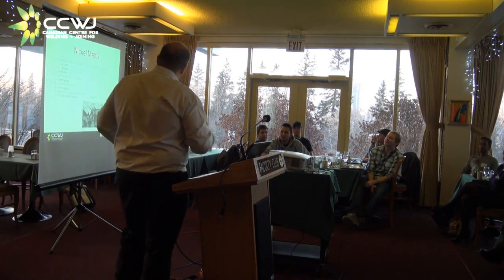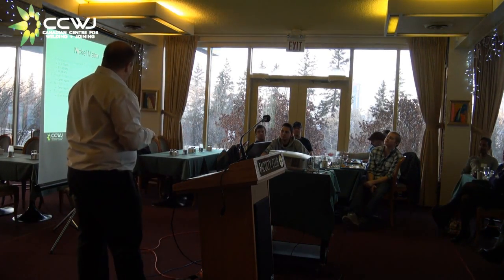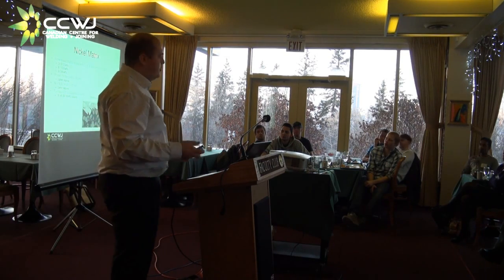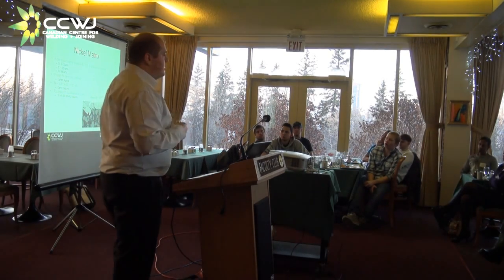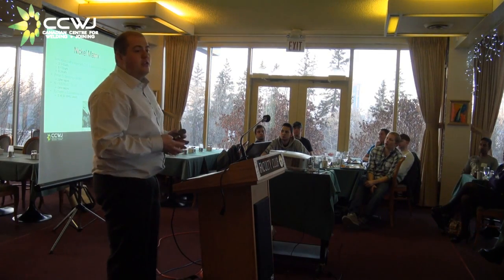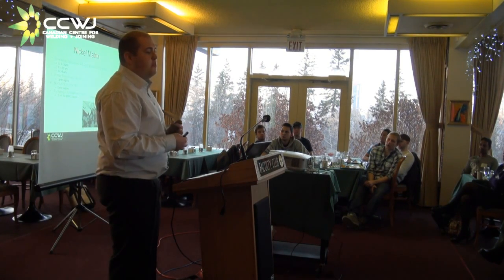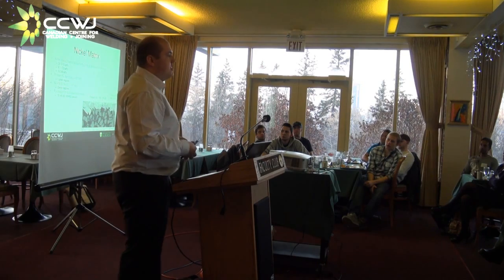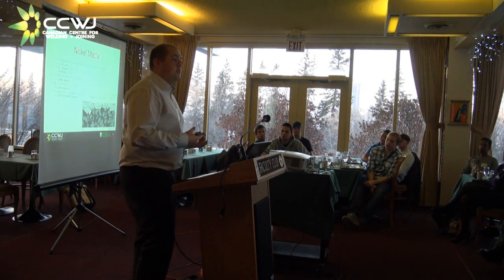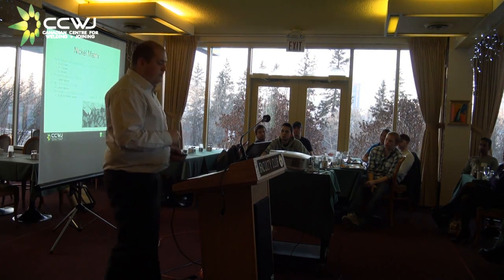So when we look at these overlays, we can see our primary gamma nickel dendrites. Those are the first form. And then in the inside we have, in the interdendritic regions, a nickel and nickel 3 boride or nickel 3 silicide hard phase. And that's what gives our matrix our hardness.